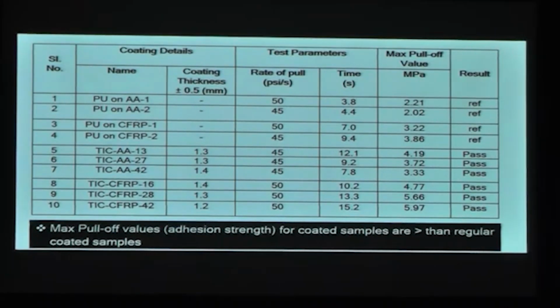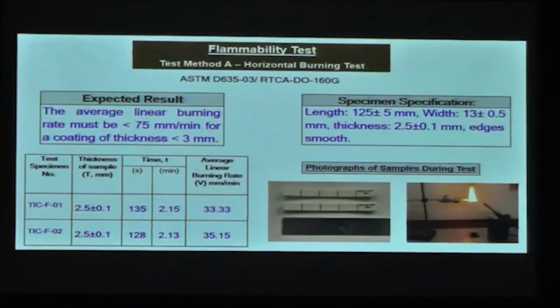All of the tests listed in the previous slide were carried out in NABL accredited laboratories and witnessed by inspectors from the certifying agencies. This was also a very important test which we had to do, wherein we carried out the flammability test using the horizontal burning test method. As per the requirement, the coating had to have a linear burning rate less than 75 mm per minute. And we see that the developed coatings had almost half of what was actually required. Therefore, the coatings also qualified these tests.